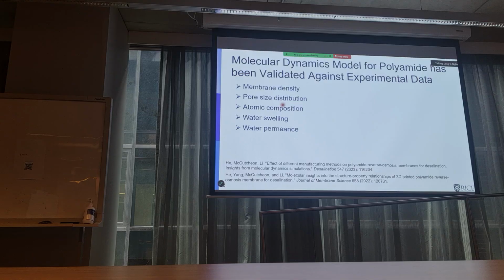Pore size distribution also roughly fits the experimental data that you determine from the pulse method. Atomic composition fits the data, water swelling fits the data, water permeance really fits the data. And more recently, we showed that the effect of pressure, or partitioning of salt into the membrane, we can simulate the data, and compression.